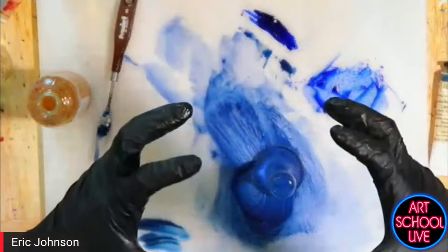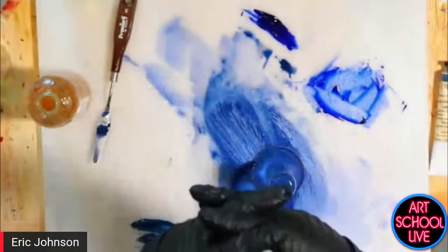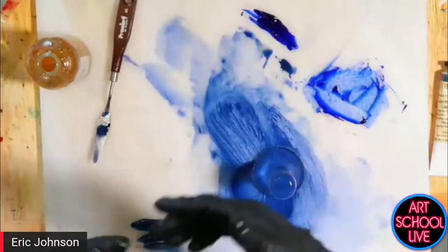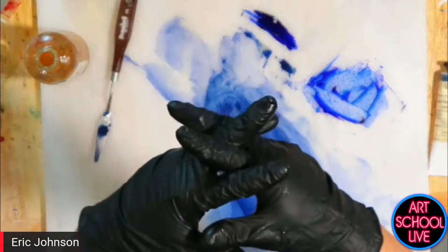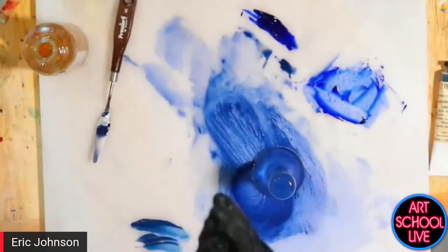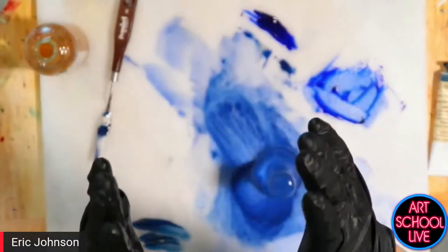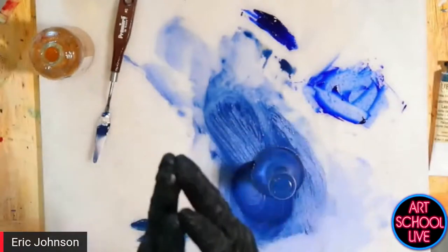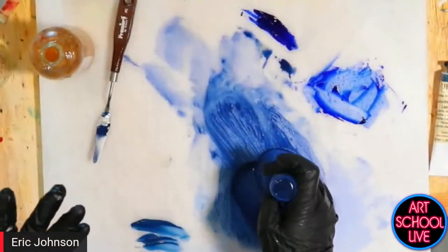My issue with walnut in particular is that when the oil dries, it swells and expands, and then over a month or so, it shrinks back to less than its original wet size. With linseed oil that expansion and contraction happens just a little, but with walnut oil the mass gets quite a bit less than it was when originally wet. That's a big issue because your paint layer expands and contracts at a greater degree, and that can be a recipe for cracking. Having said that, there are hundreds of years of Dutch artists using lead white in walnut oil, and Sargent used lead white exclusively in safflower oil. So it depends on what you're going for.